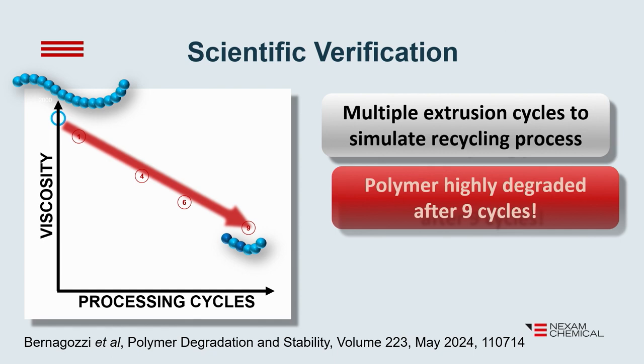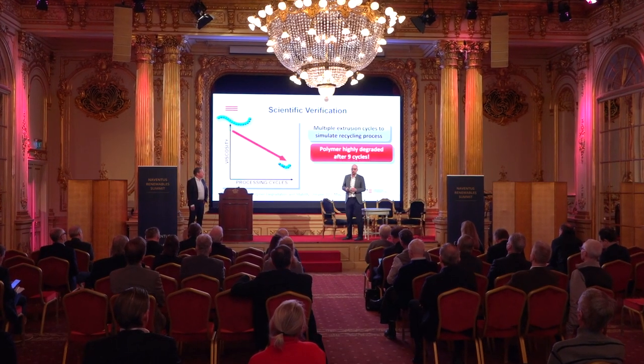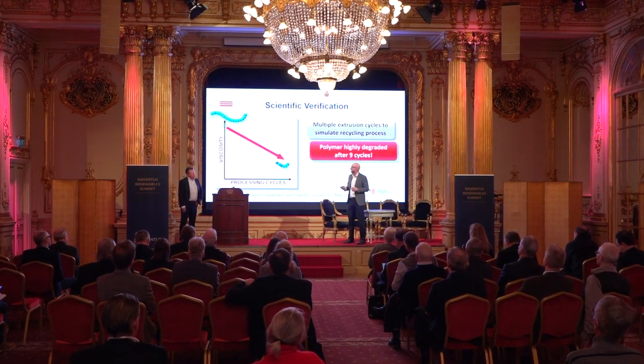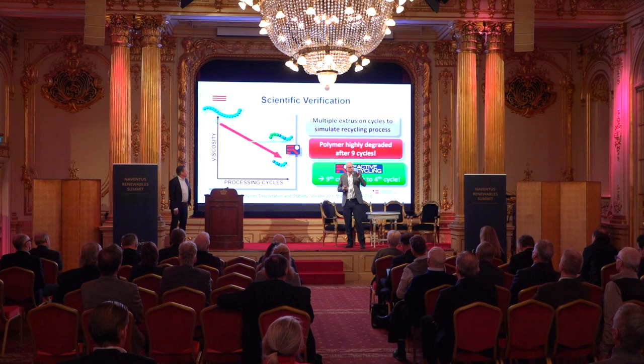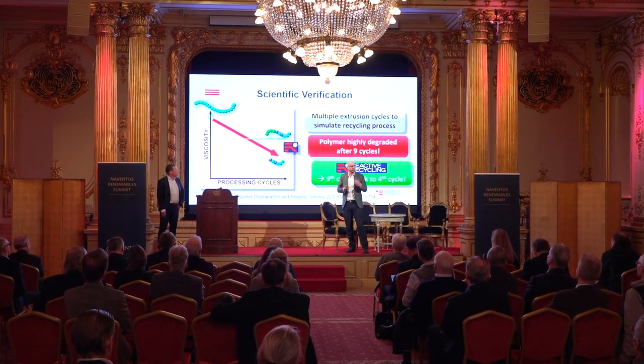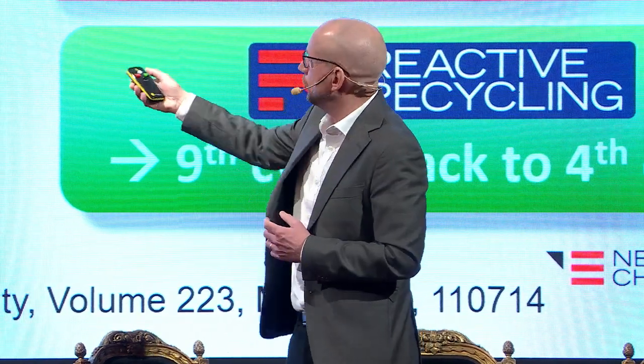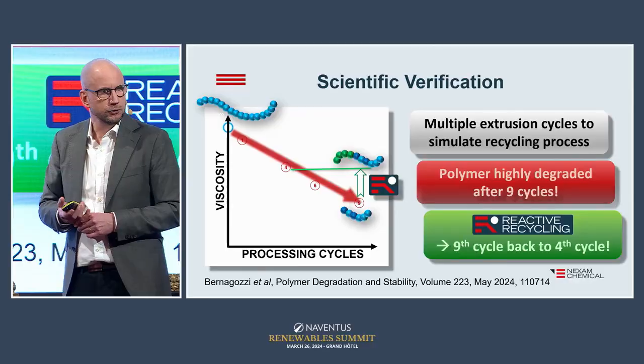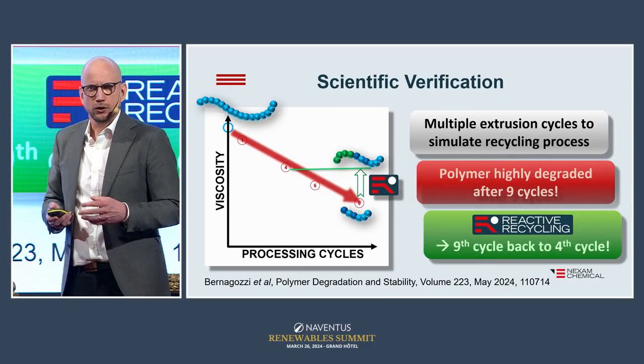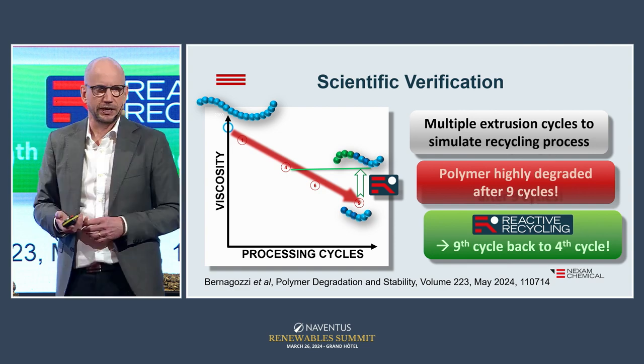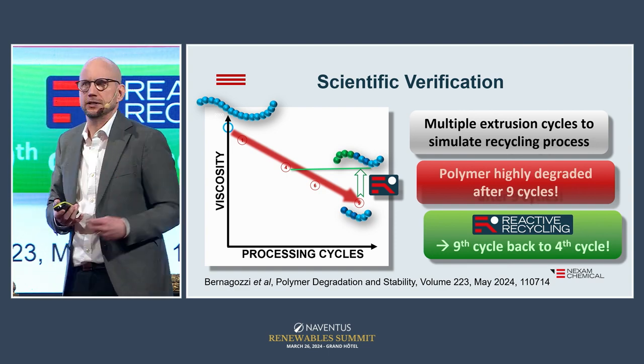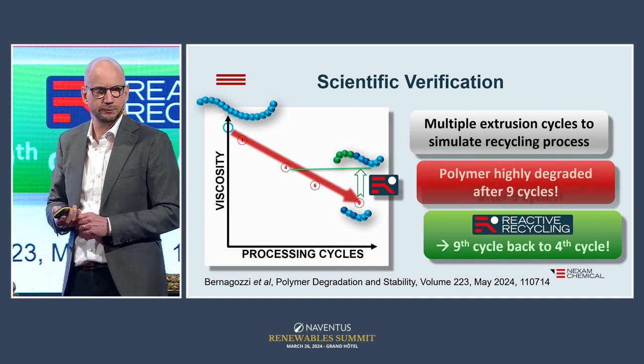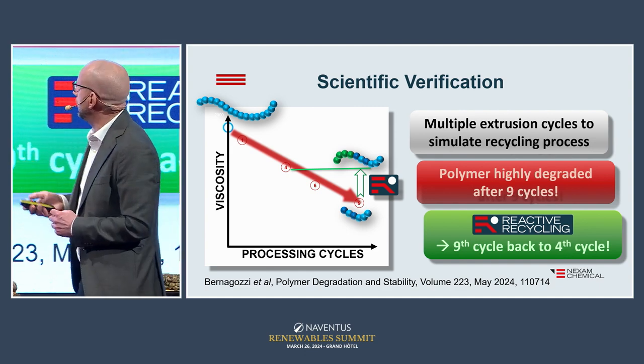So at the end of this 9 cycle, this here is very, very difficult to use for basically any application. The good news is that if we take this highly degraded material, we put in our additives, and we use reactive recycling, we're able to build it back up. We are building molecular weight, so we're putting it back from what was a really bad material into something that's corresponding roughly to the level 4. So we are actually now increasing the value of this material and increasing the application range where these can be used. So we are really rebuilding molecular weight.